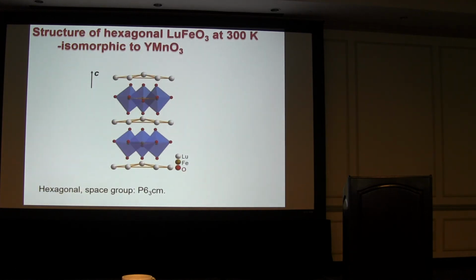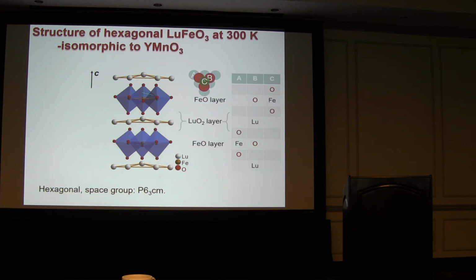Let's just take one more look at the hexagonal structure. This is kind of a layered structure material, and you can see that it's quite interesting. The rare earth actually has its own layer, and of course, iron and oxygen will share one layer. Another quite special thing in this material is the local environment of iron. Instead of 6-coordinate, this is a 5-coordinate system, and you will see that this plays quite an important role in many properties in here.